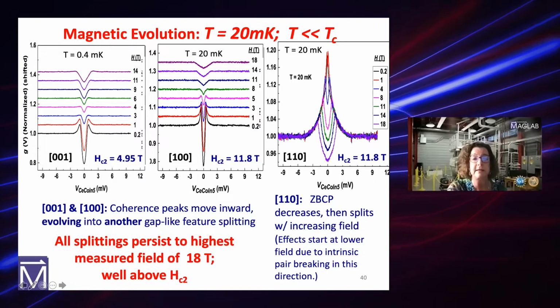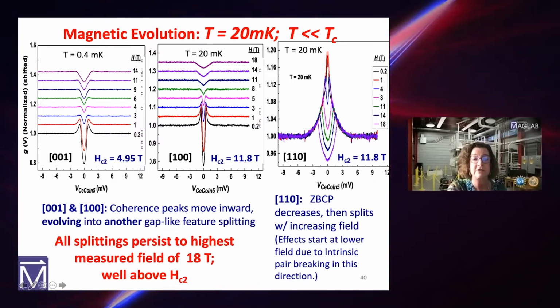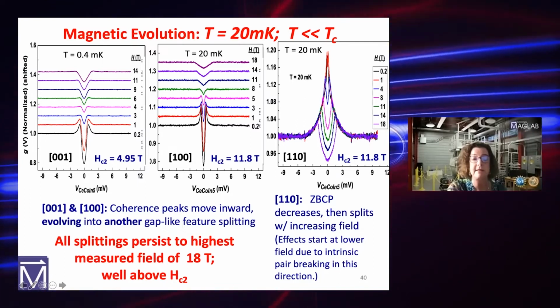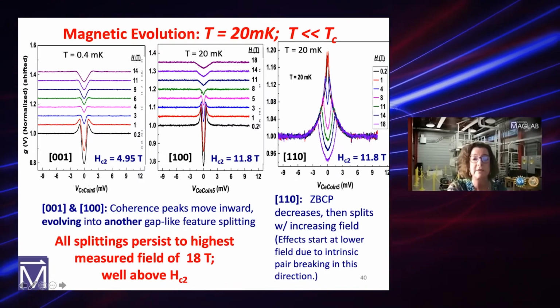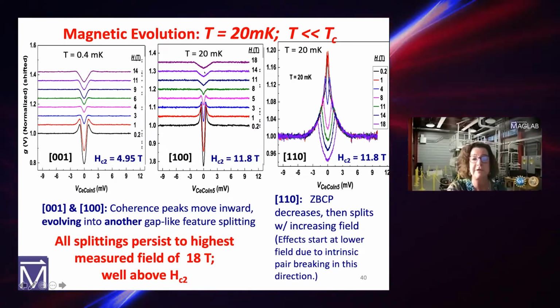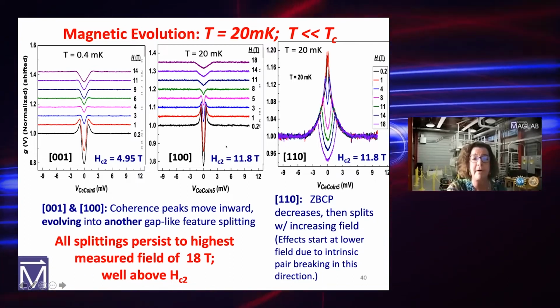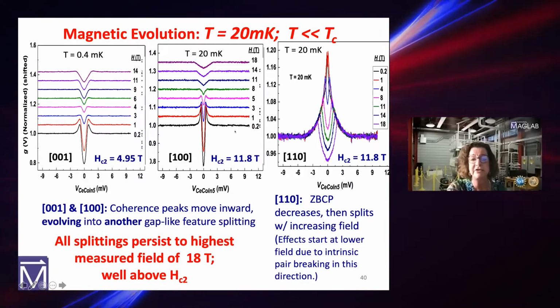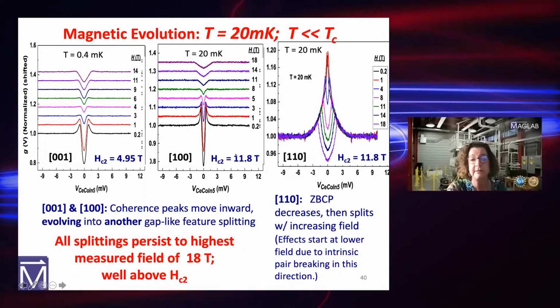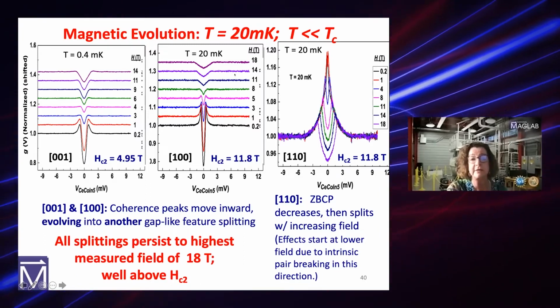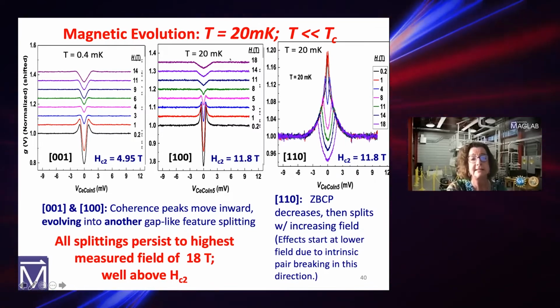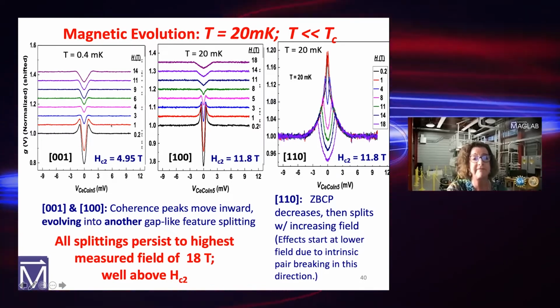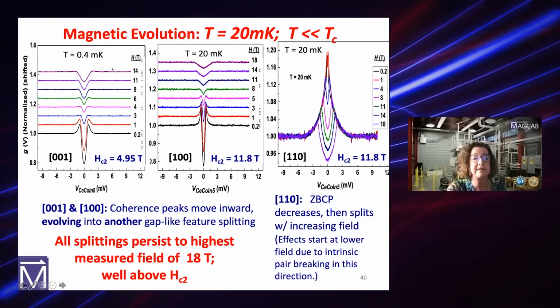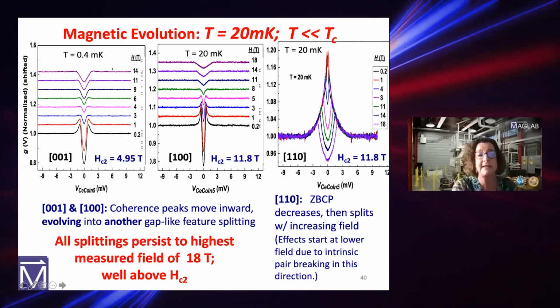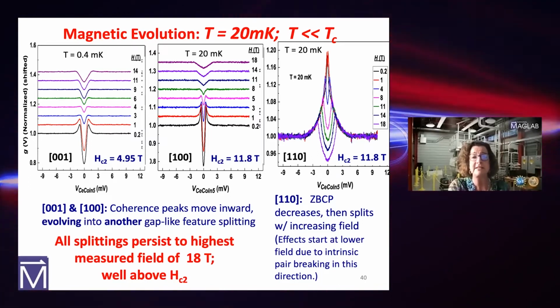That's also true in the 100 orientation. This is the superconducting gap. And as we raise the field, we notice that it starts looking like a superconductor, and it starts looking like some other gap comes in here. Now, I want to point out in both these things that this gap-like feature persists above HC2. HC2 in the 100 orientation is 12 Tesla, so that's here. And look what's going on in 14 and 18 Tesla. In this orientation here, HC2 is about 5 Tesla. And look where we are at 6, 9, 11, and 14 Tesla. There can't be any superconductivity in there. So there's some gap in there that's increasing with increasing field.